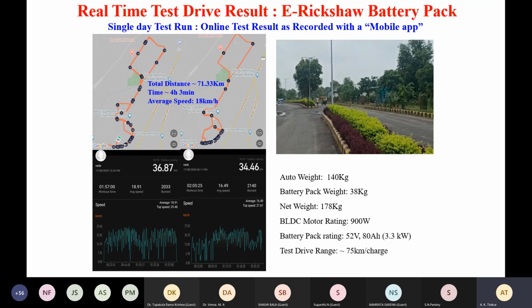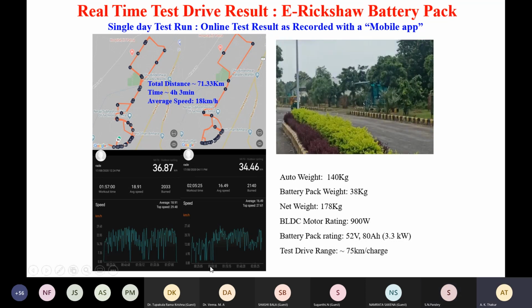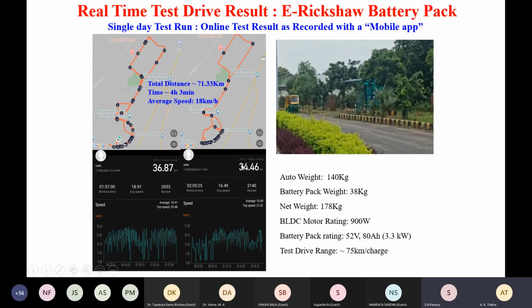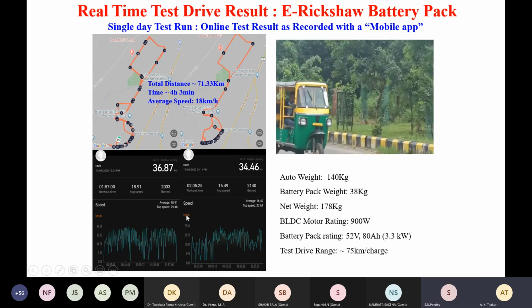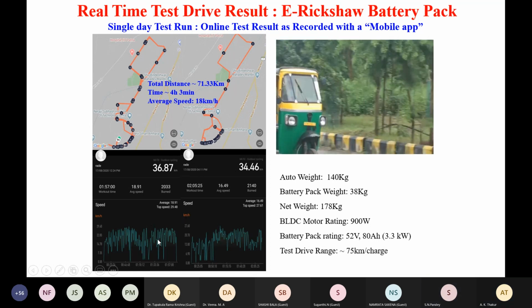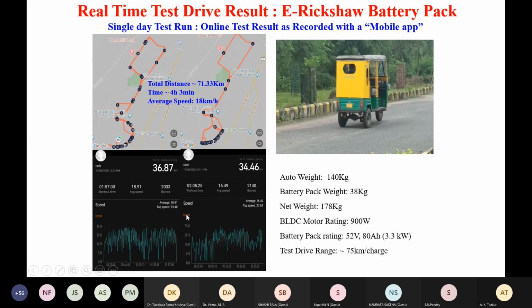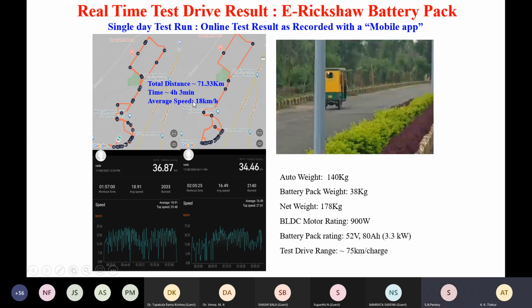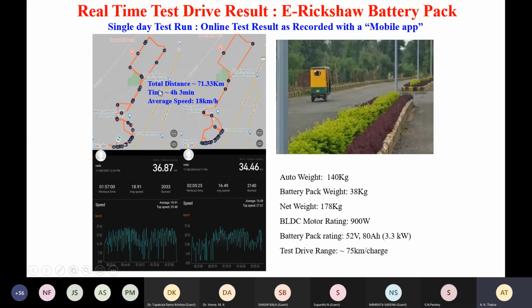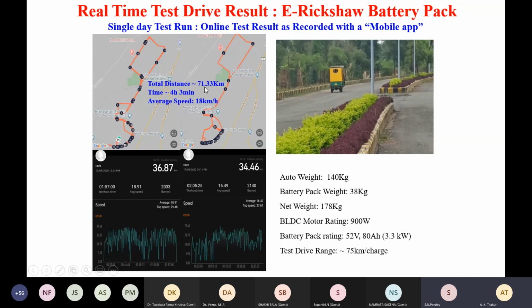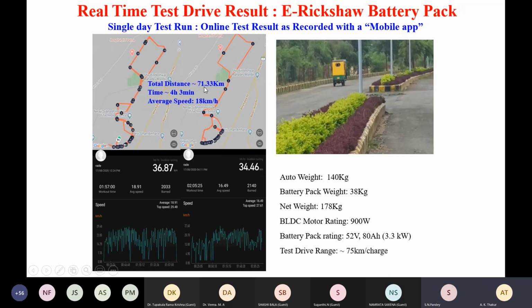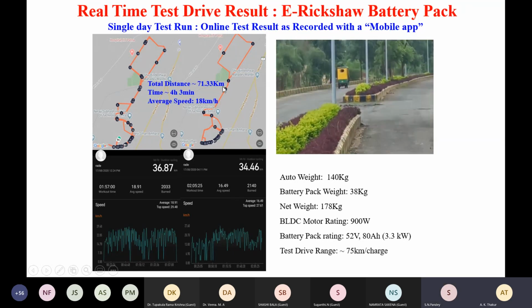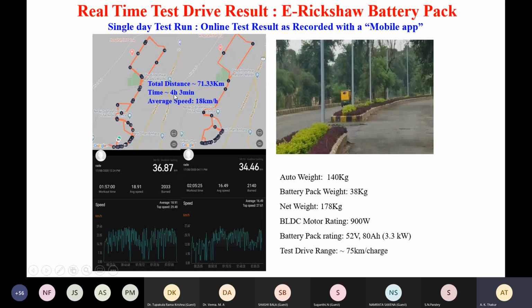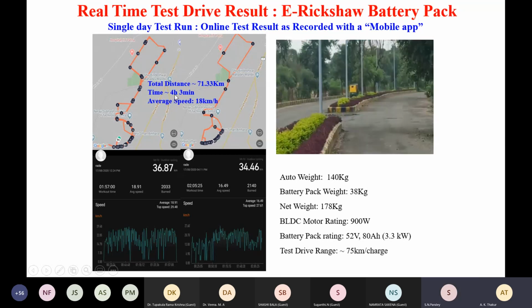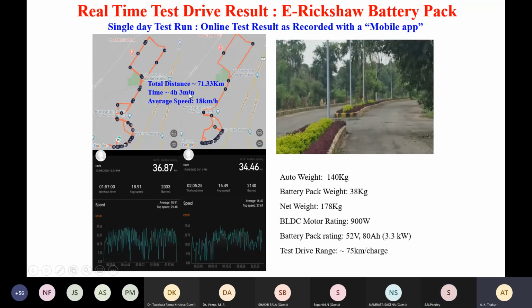And here is the online test report during drive. How much is the range of travel recorded through an app while driving? One full charge allowed this e-rickshaw to drive 71.33 kilometers in one charge that lasted for 4 hours 3 minutes with an average speed of 18 kilometers per hour.